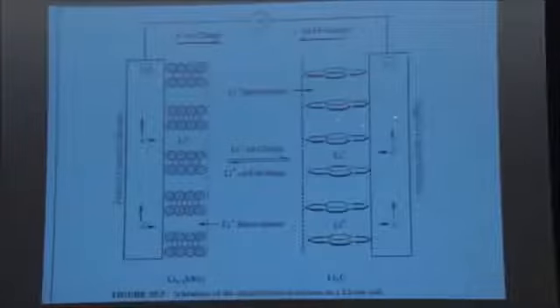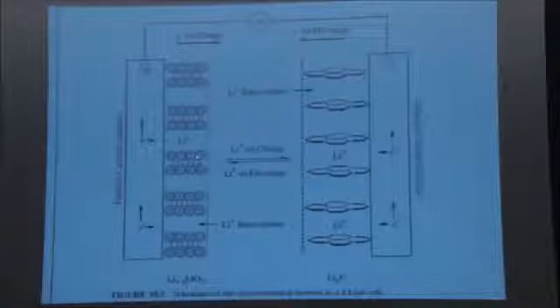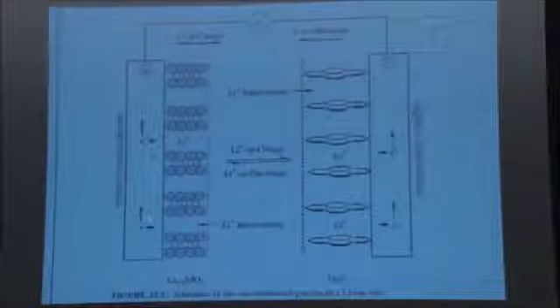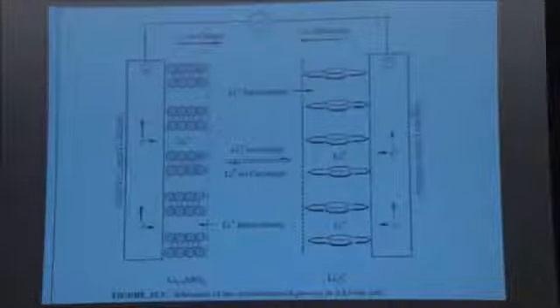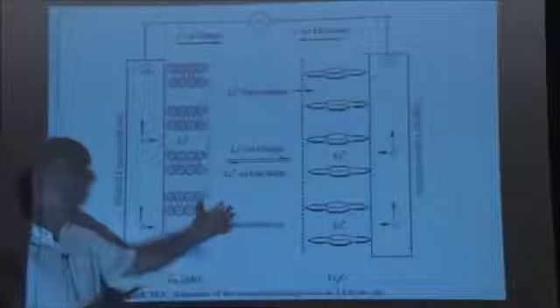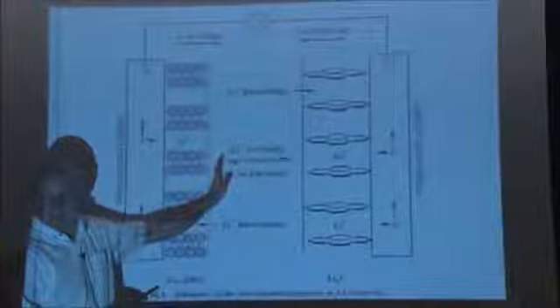And once the lithium ion cell is charged, now the lithiated graphite, graphite with lithium inside, is very reactive. It's reactive like lithium metal. And the lithium transition metal oxide with missing lithium is also very reactive. And what happens is both of those electrodes actually react with the electrolyte solution that they're in contact with. And you would say, well, then how do you make a battery that has any lifetime at all if the electrolyte reacts with the electrodes?